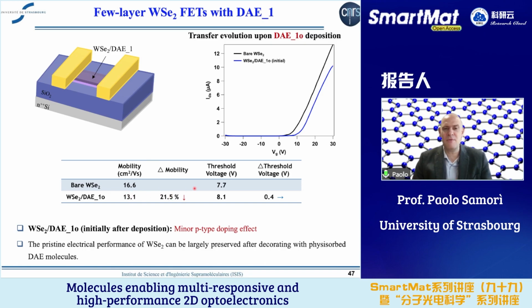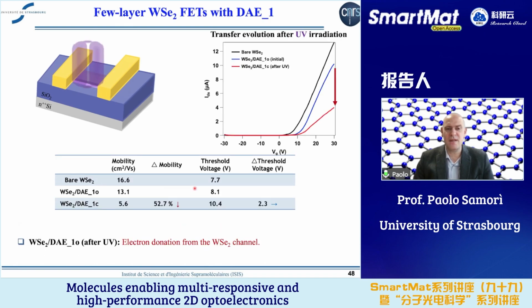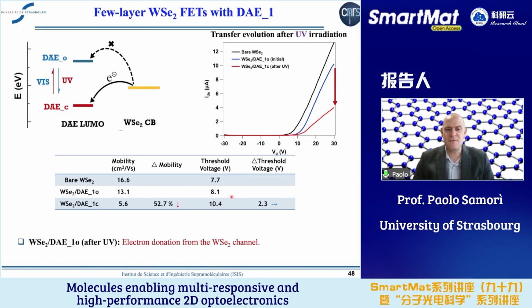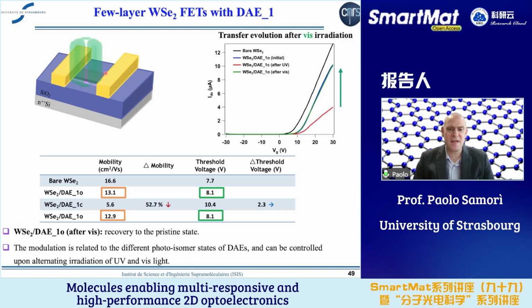Then at this point, what we can do is irradiate with UV light to trigger the isomerization from the open to the closed state. And you can see that this is accompanied by a very strong reduction of the electron mobility of 50%, and actually an increase of the threshold voltage. Then we can irradiate with visible light in order to bring the diarylethene back to the open state and stop this kind of charge trapping. And you can see that with illumination with visible light, we fully recover the initial mobility of 13, and also the threshold voltage is fully recovered.